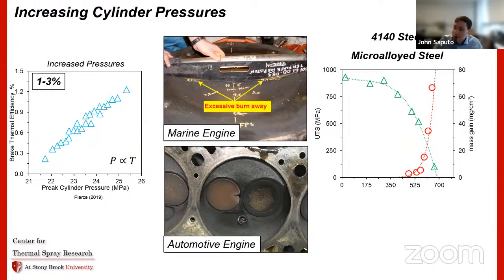So as you increase the temperatures in these systems, two things happen. One is that you start to oxidize. You have hot corrosion in these systems as well, but we won't really get into that. And then the second thing is that the tensile strength or the yield strength of these materials will start to bomb out around 400, 500 degrees.